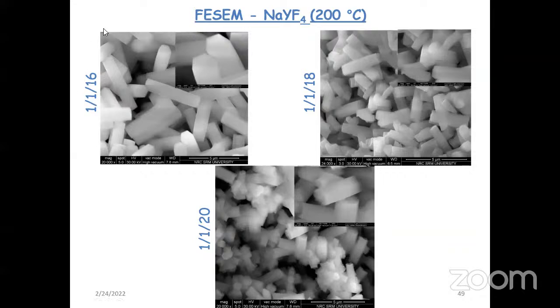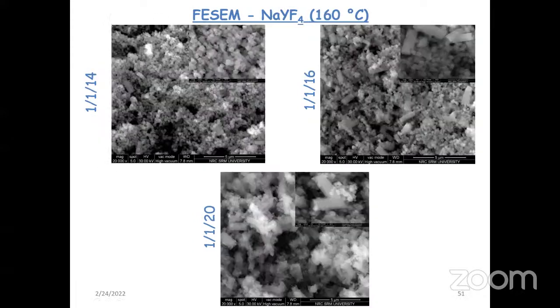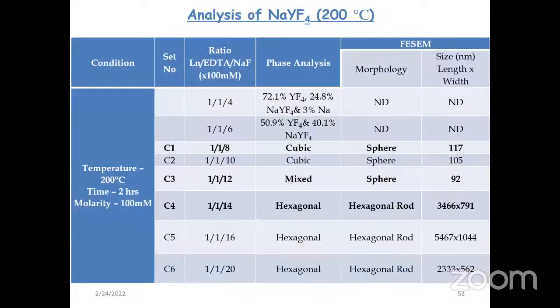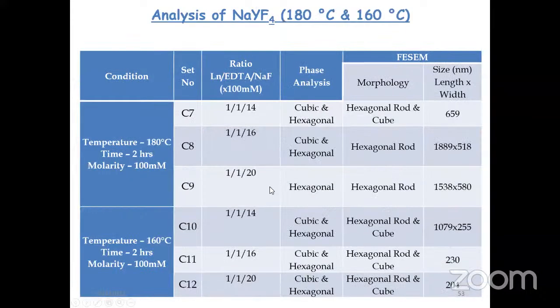When you increase the sodium fluoride concentration and decrease the temperature, you find very clear rod-like structures. This is at 160 degrees Celsius. At 200 degrees Celsius, by varying the concentration of sodium fluoride, we are able to get spheres as well as hexagonal rods. When it comes to hexagonal rods, the size increases. Similarly, at 180 and 160, we could find hexagonal rods as well as cubic.